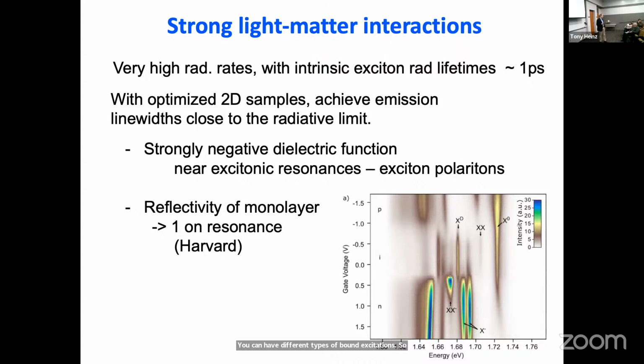I should say that to get to this radiative limit, you do have to be at reduced temperature. So you need a good sample, but at room temperature, you have a lot of phonon scatterings. You're not in this limit. But it's not extremely low temperatures. It's sort of 10 Kelvin kind of range. So it's quite an interesting regime to explore, I think.